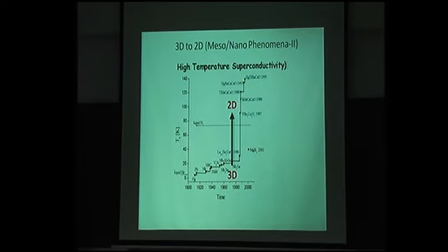Okay? So high temperature superconductivity cannot be observed, it's almost like a theorem, in a 3D system, number one. Number two, before that we thought that oxygen may be essential, but now there are different systems where oxygen is not there, non-oxide systems. But the other thing on which we have consensus is that these are completely new physics, which is called strongly correlated physics. It's not like Bloch-Mott physics. Mott shows that a completely different kind of physics can be involved if the electron-electron interaction in your system is stronger than any other energy scale. Okay, but the point I want to emphasize here is that you can observe this novel phenomenon only in 2 dimensions.